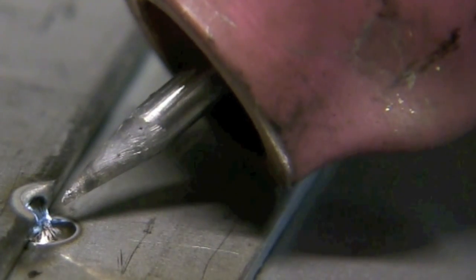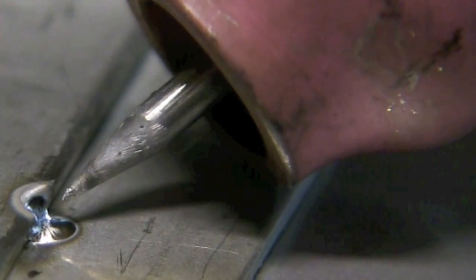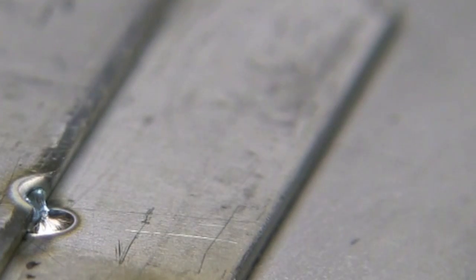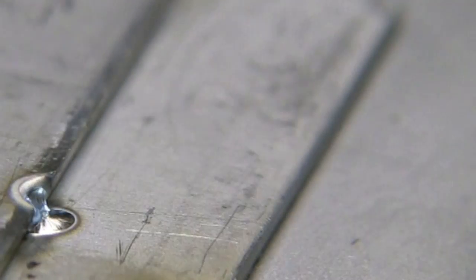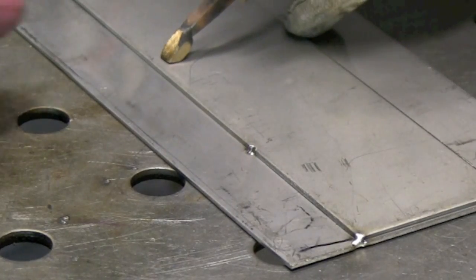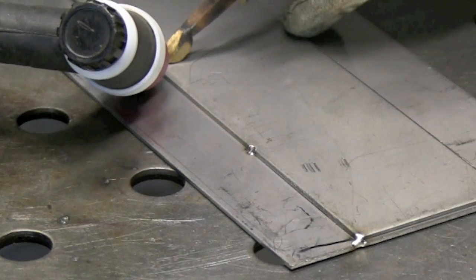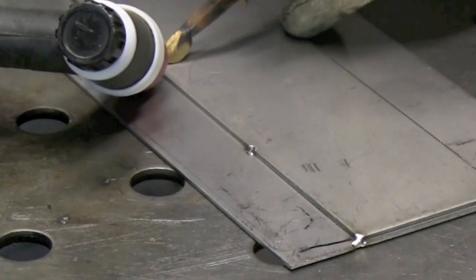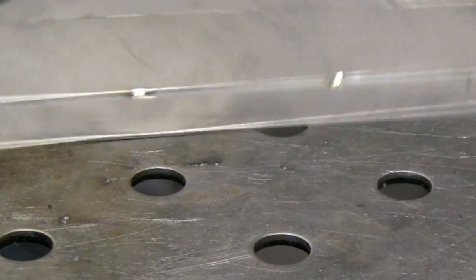Now here's a little close-up of that. I just prop the cup on there, point the tip of that electrode right where I want the tack, give it a quick blast of amperage, and now I've got a really small, tight, clean tack that hardly discolors at all and typically won't melt through because it's so quick.